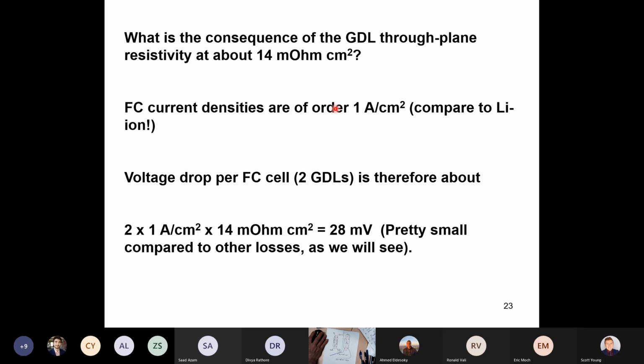And when the current densities are this massive, you really have to worry about every little bit of electrical resistance you have. So what's the voltage drop per fuel cell? You have 2 gas diffusion layers, one on the anode side and one on the cathode side. So you got 2 layers, 1 amp per centimeter squared times 14 milliohms per centimeter squared gives you 28 millivolts. Okay. So out of a fuel cell open circuit voltage of around 1 volt, this is pretty small. And this is pretty small compared to the other losses that take place in a fuel cell, as we'll see going forward. Any questions about that?